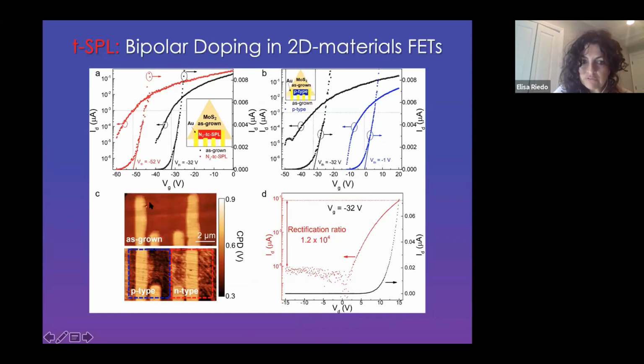Again, the electrodes have been fully deposited with t-SPL. So the whole device, from doping to electrode fabrication, has been completely fabricated with thermal and thermochemical lithography. And this is the rectification ratio, 10 to the power 4, of the diode, which is really an extremely good result, comparable with state-of-the-art PN junctions in molybdenum disulfide.